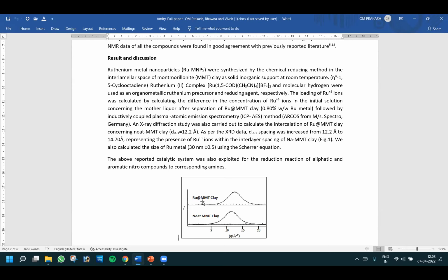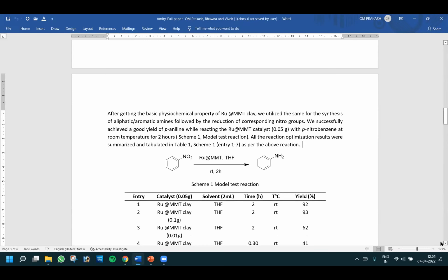We utilized the same for the synthesis of aliphatic and aromatic amines by reduction of the corresponding nitro group. We successfully achieved a good yield of aniline by reacting nitrobenzene with ruthenium MMT clay at room temperature for 2 hours, as shown in my scheme. All the optimized reaction results are summarized in my tables.